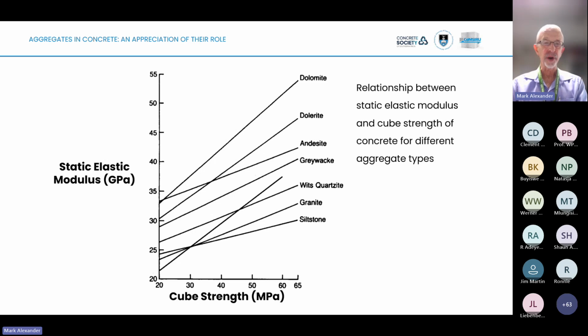Here you can see an even more graphic outcome of some of the testing we did. Here are a whole bunch of aggregates here. They vary from dolomite through dolerite, andesite, greywacke, all the way down to siltstone. And if you look at a typical concrete strength, let's take 40 megapascal, you can see the modulus of the concrete could be somewhere around 25 to 28, all the way up to 45, almost double the elastic modulus of a concrete of given strength. Now, once again, not all these aggregates will be available in every geographical area. But if you want a concrete of high elastic modulus, you need to really go for what we would here call a Transvaal dolomite. Not every dolomite does this, by the way, but these are the Transvaal dolomites. Really, really superb materials in giving you high elastic modulus. We used this to good effect when we were doing repairs on the M1 motorway in Johannesburg many years ago, when we needed to do an infill concrete of very low deformability. So that is a very interesting graph.